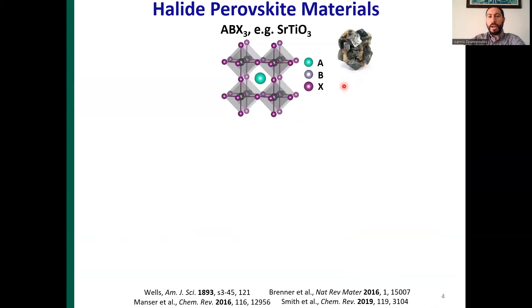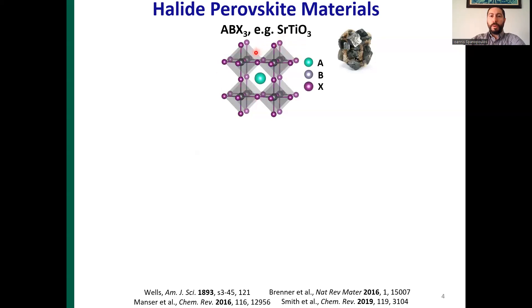One very important family of semiconductors is the family of halide perovskite materials, and especially the hybrid halide perovskites. These compounds were named after the naturally occurring mineral perovskite, or calcium titanate. The general formula is ABX3, and the structure consists of corner-sharing BX6 octahedra that propagate in three directions, whereas in the formed cuboctahedral cavities, A-site cations reside, charge-balancing the structure. When these compounds were discovered, they thought calcium titanate was cubic at room temperature; however, it is orthorhombic. Therefore, when we refer to the cubic aristotype structure of perovskite compounds, we refer to the structure of strontium titanate, which is cubic at room temperature.